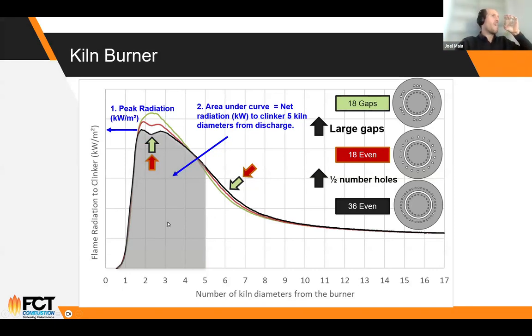So what this means is that in the green configuration, the grouped 3 by 3 holes, we can achieve a much more intense and short flame. On one side, this is good because alternative fuels are a little bit harder to burn. So you want to have an intense flame to allow a higher substitution rate by these alternative fuels.